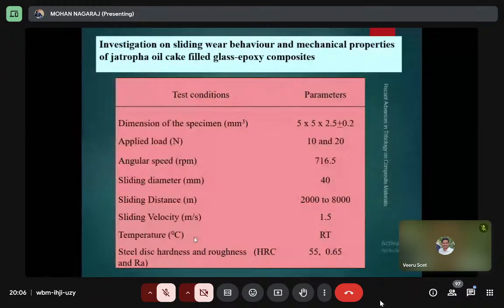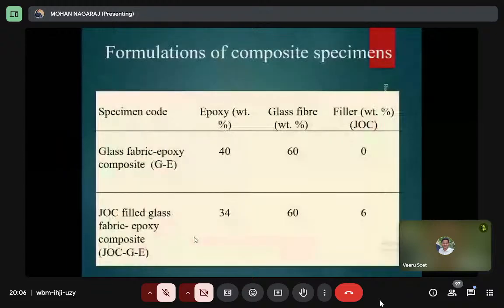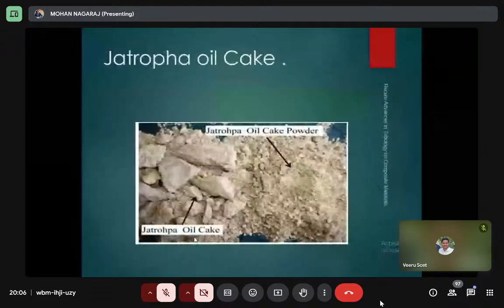not at high temperature. So we observed this is the glass epoxy with the filler Jatropha up to 6%. This is the natural composite, a natural filler. After extraction of the oil from the Jatropha, we are using the Jatropha oil powder. These are all the mechanical properties. By introducing